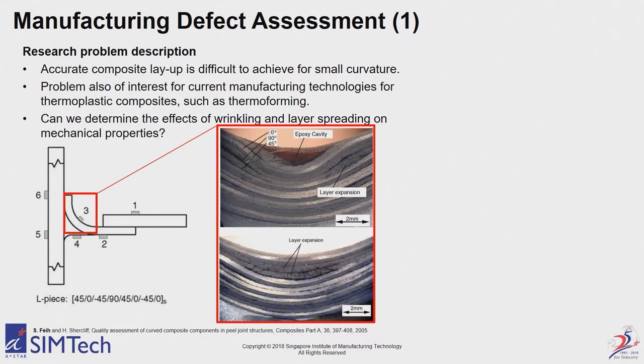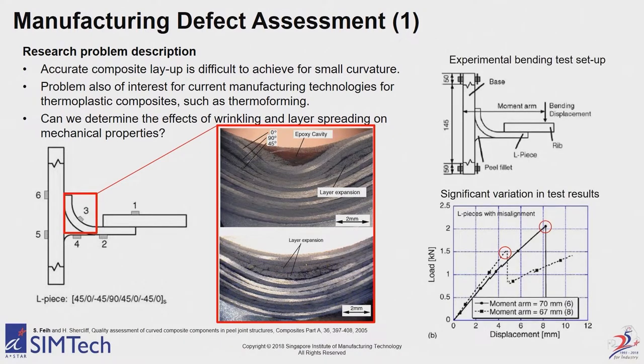Now, keep in mind, that was in 2002. So at that point, analysis was definitely not as far progressed as nowadays. And we actually did a couple of tests, some under bending, some under tension. And the one thing we noticed was there was a lot of variation in the results. Way too much variation for our liking, way too much variation for an aerospace industry that actually needs to have very well certified parts. So the question was, why does this happen? Is this linked to the manufacturing defects? We assumed yes, but obviously it was something that we wanted to confirm.